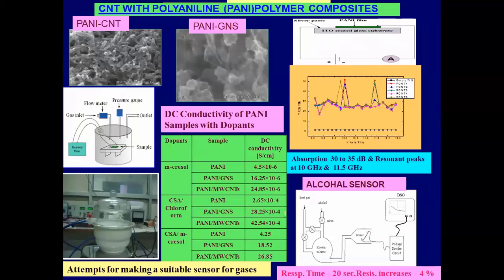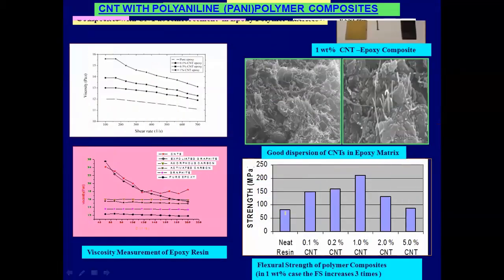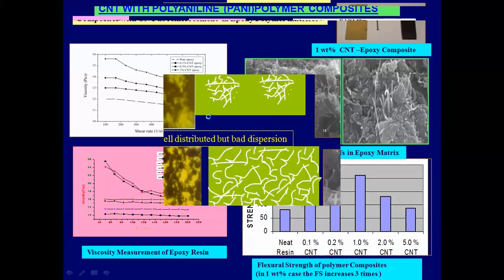Now, applications such as sensors, electrical conductivity measurement, or EMI shielding measurement were all conducted. As I told you, when we tried to disperse these nanotubes into a composite, you can just imagine, compared to the epoxy without any CNTs, with just 1% the epoxy completely becomes a black plate. So with a low concentration, you can disperse the nanotubes in such a way that they can perform because of their unique properties. Once we made the composite, you can see it is highly dispersed.